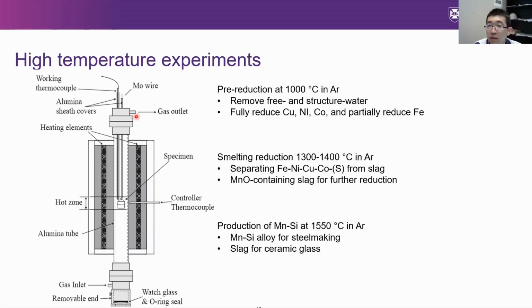So here is our high temperature experiment, and this is a schematic of the high temperature furnace we normally use. At high temperature, we normally refer to over 1000 degrees, and this high temperature furnace can even reach up to 1650 degrees. So it is made to fulfill our experimental purpose.